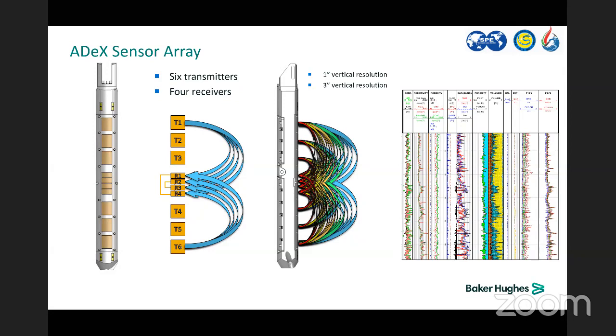One of the specs will help us with shale sand lamination: we added extra frequency, extra transmitter and receiver, which help us to get like 1-inch vertical resolution. So, resistivity independent, you are able to get your hydrocarbon saturation or water filled porosity in 1-inch vertical resolution. You can see the example. Even if it's not similar until now, I'm trying to deploy it in turbidite, but in the shale sand sequence, you can see that we are able to identify the hydrocarbon and the water filled porosity there.